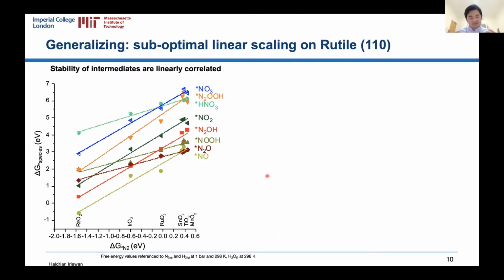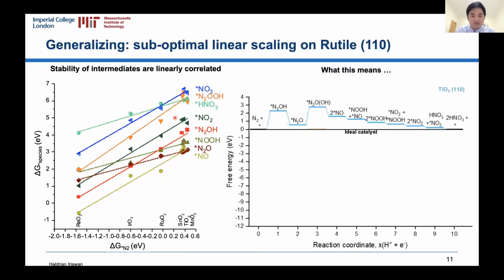So we can take a step back from these specific surfaces and look at the general trend. I've plotted here the free energy of the reaction intermediates, which represent the stability of these species on our surface, as a function of the N2 binding on the surface for the different types of rutiles computed. What is really the fundamental limitation here is that the stability of these reaction intermediates are strongly correlated with each other in a linear fashion, and the gradients are quite similar to each other, either m equals 2 or m equals 1. And this linear scaling is very, very fundamental.